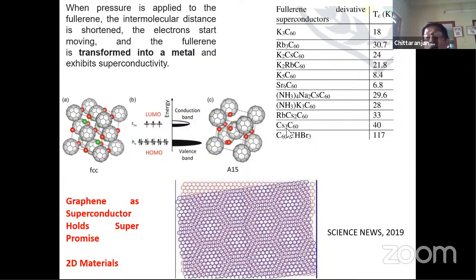You see the cesium C60, its critical temperature is 40 K, while C60 in the presence of CHBr3 chromophore has a critical temperature of 117 Kelvin. That means the target of researchers is to design a room temperature or high temperature superconductor. The problem is that these materials, the graphene or even some metals, all undergo some changes with time. This frustration with these materials leads to the design of mixtures of metals as well as organic components, that is, the hybrid materials, inorganic and organic hybrid materials.